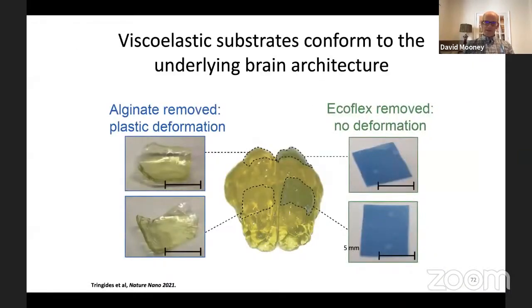These viscoelastic arrays actually conform to underlying brain architecture very well. So here we're looking at an agar model of a sheep brain. And if we use Ecoflex, a typical material, it doesn't conform very well to the underlying brain tissue. When you remove it, you can see it has undergone no deformation. When we use one of these alginate materials instead, it will actually plastically deform or flow to precisely match the underlying geometry of the brain tissue, as one can see when it's removed after some period of time.